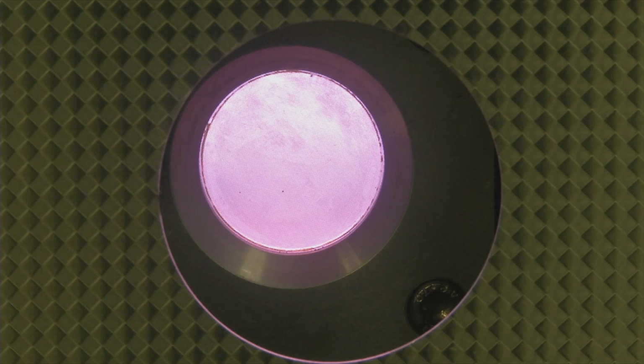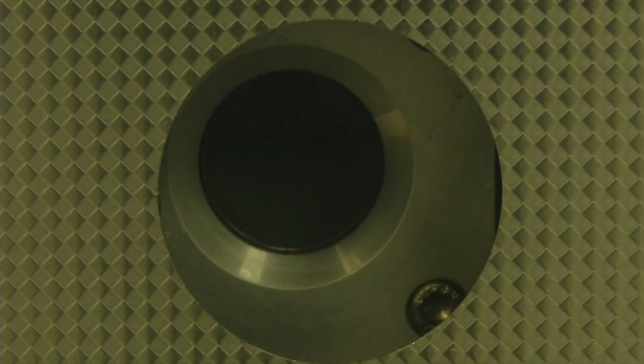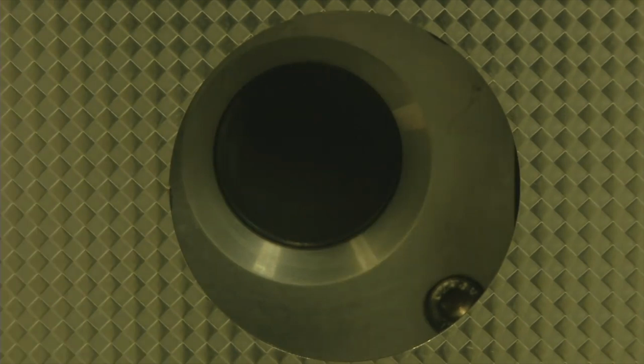In addition to all the other processes that we have, this emission process is the one that is giving us this nice glow, right? This is the first step in this whole etch process. Now the flash is gone, and we are moving to the second step. In this step, we are etching silicon, the underlying silicon, where we are doing an isotropic etch of silicon using fluorine chemistry.